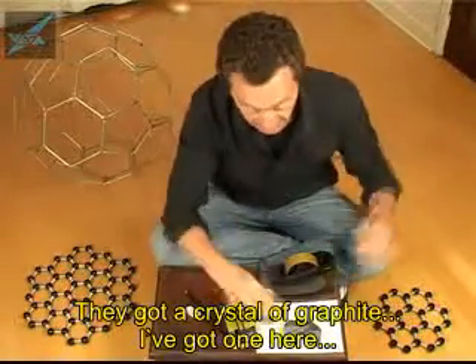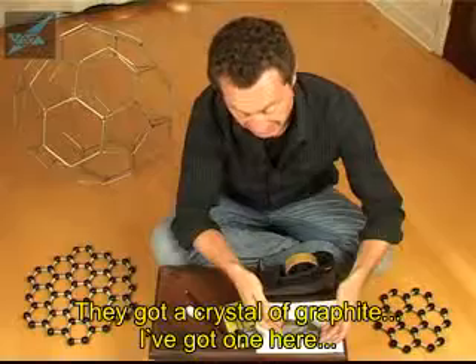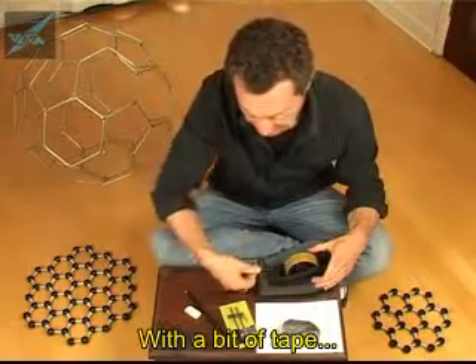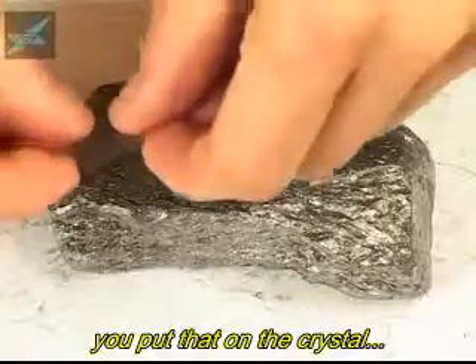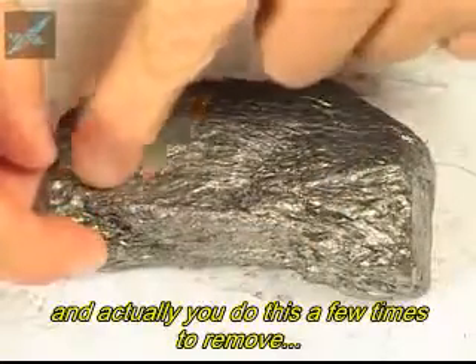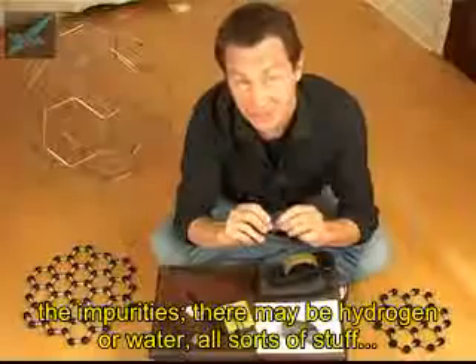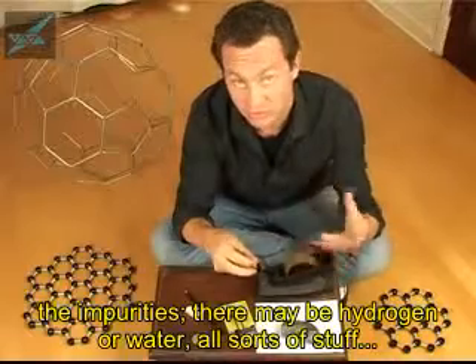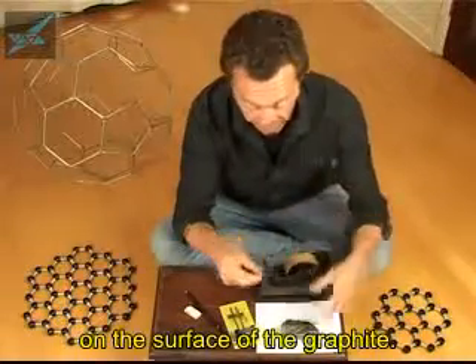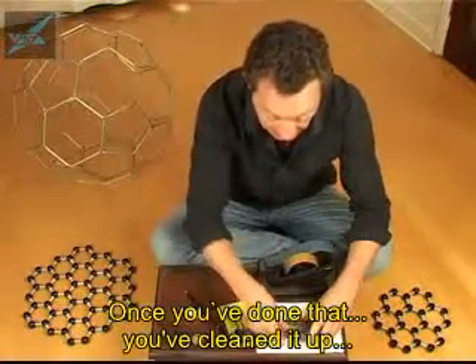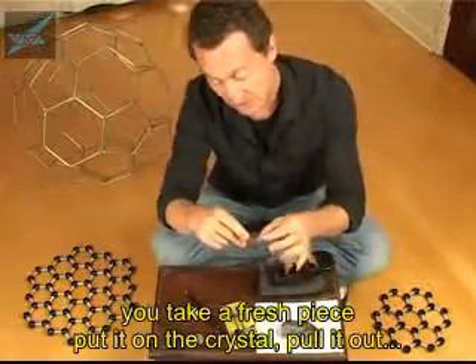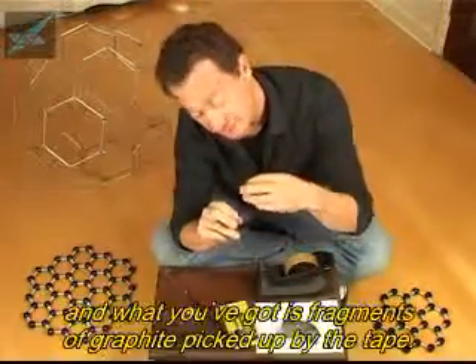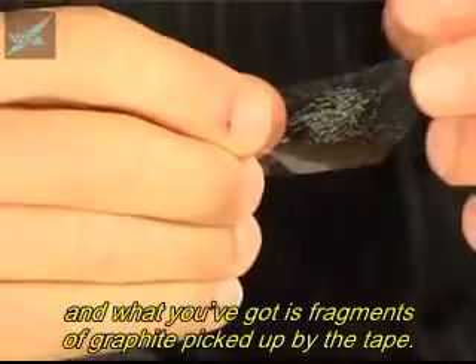What they did was they got a crystal of graphite, I've got one here, and with a bit of tape, you put that on the crystal, and actually you do this a few times to remove the impurities. There might be hydrogen and water and all sorts of stuff on the surface of the graphite. But once you've done that and you've cleaned it up, you take a fresh piece, put it on the crystal and pull it out. And actually what you've got is fragments of graphite picked up by the tape.